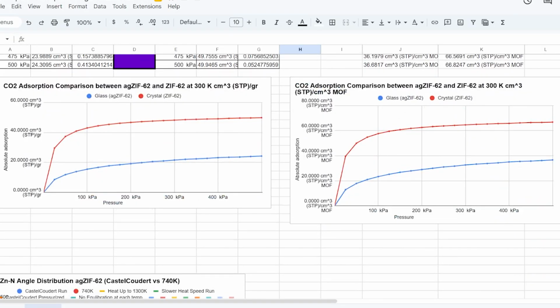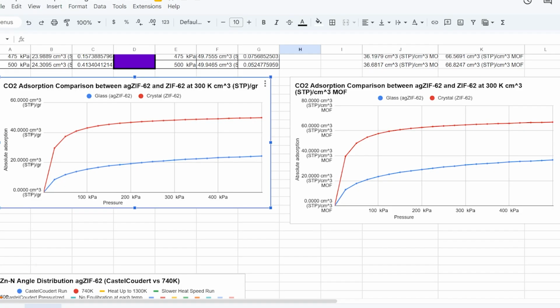Now, comparing crystal to glass, the difference is visually quite large when measured per mass. The crystal clearly dominates. However, when normalized by volume, the gap becomes smaller, though still significant. At higher pressures, the crystal still outperforms the glass, but not by an order of magnitude, more like a factor just under 2. So overall, the takeaway is quite clear.